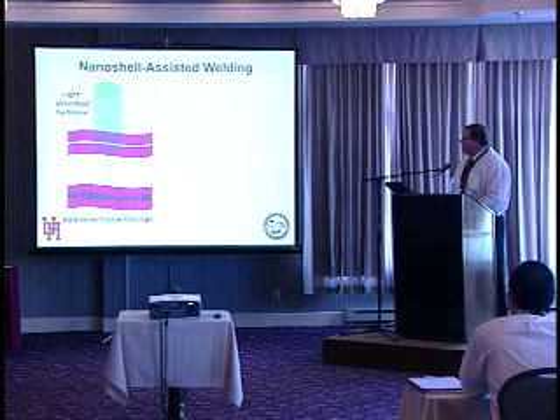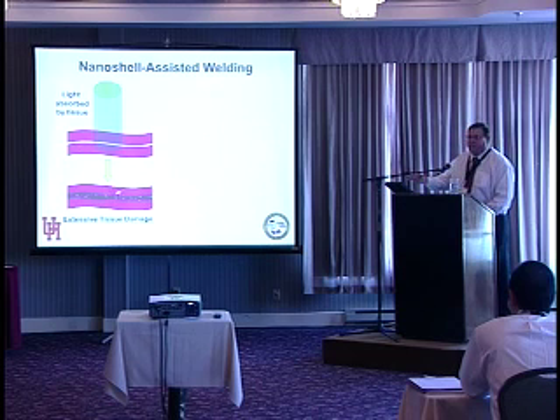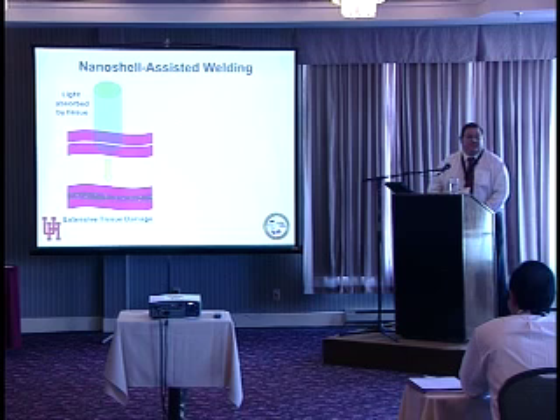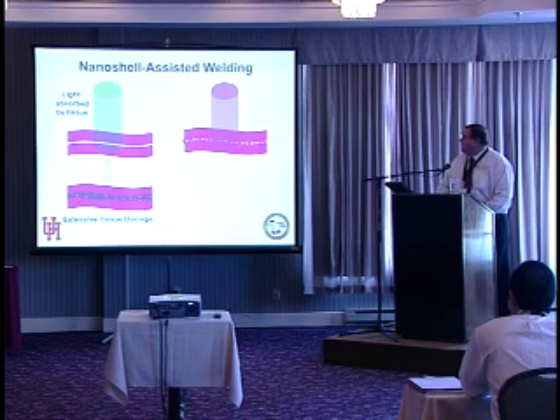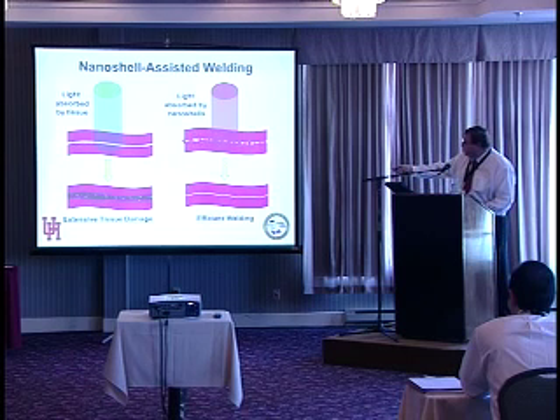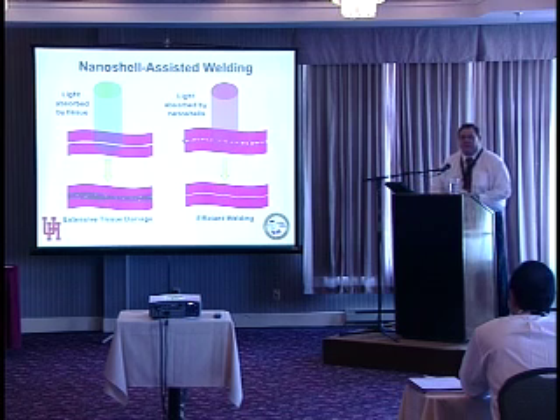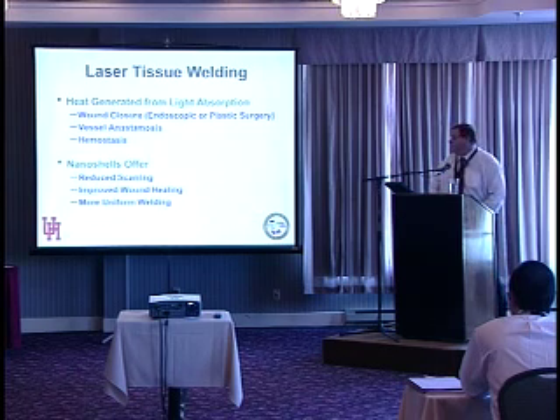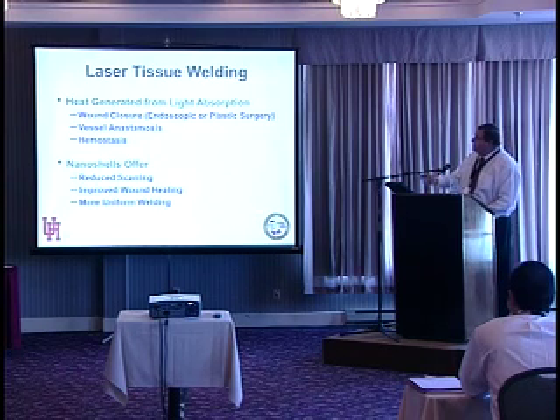heating. So this process has advantages over trying to do laser tissue welding with, for example, ultraviolet wavelengths, because those wavelengths will cause extensive damage to the tissue. If you do the nanoshells, you can take two pieces of tissue and layer your nanoparticles in there in a very localized area, and then when you shine your laser light, you can get efficient welding without too much damage.